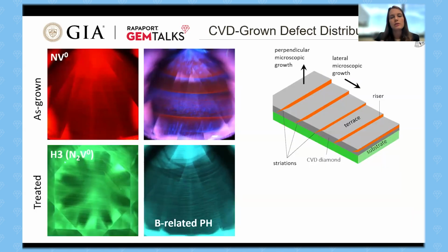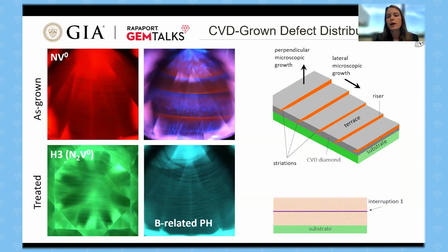For the CVD grown diamonds, this is proceeding by layer growth, and it's going to create these ripples, these terraces and risers as it's growing. And again, the incorporation is going to vary between those risers and terraces, and it's going to create a very distinct set of patterns. So these striations, as they're known, are these tightly spaced lines that are diagonal. And then if there are any interruptions during growth, you might also have a huge change in the impurity incorporation, creating these layered structures that by eye you might not be able to see, but by using fluorescence imaging, they can be clearly revealed. And if you were to look at this and you have the experience of having looked at a lot of natural diamonds, you would immediately say this is a lab-grown diamond. So this is very conclusive.